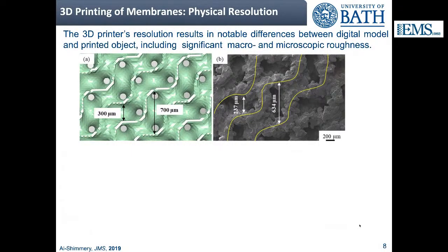And finally, there is the physical resolution of your printer. What you see on the left is the digital object of our 3D printed membrane, and you can see it has a very regular shape, very good circular pores. And this is what you obtain when you print. Consider these images are now a few years old, but at the time, this was a top-of-the-line commercial industrial 3D printer with a nominal resolution of 16 micrometers. And in reality, the resolution was significantly poorer than that. You can see that the printed object is not exactly what was in the digital object, but nonetheless, you get that kind of shape.